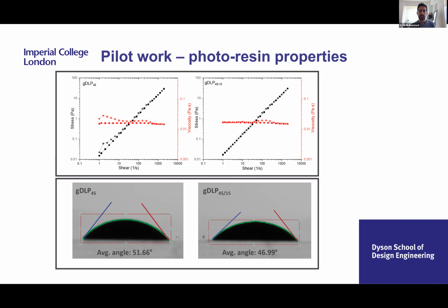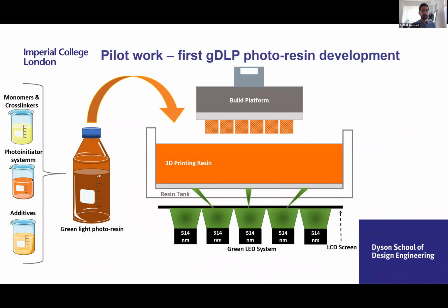We also studied the contact angle of the photoresin on PDMS and FEP film. FEP film is what is used in the tanks of DLP and LCD printers. We wanted to ensure there's an even distribution when the resin is applied in a low volume, so that it spreads rather than clumps together. This is essentially the setup. It's a scheme showing the setup of our printer, where we add the photoresin to a resin tank, and the green light goes through the LCD screen, and you get the 3D printed scaffolds, or the 3D printed cubes.